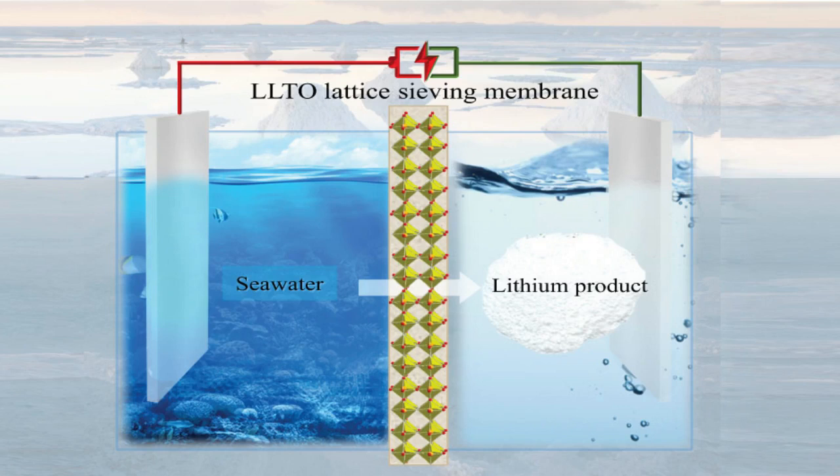This lithium-enriched water then becomes the feedstock for four more cycles of processing, eventually reaching a concentration of more than 9,000 ppm. Adjusting the pH of this solution delivers solid lithium phosphate that contains mere traces of other metal ions, pure enough to meet battery manufacturers' requirements.